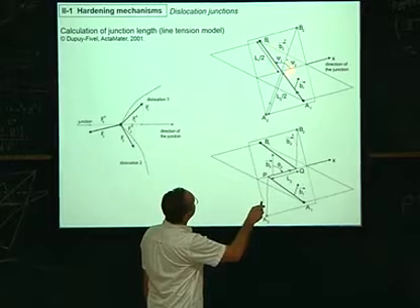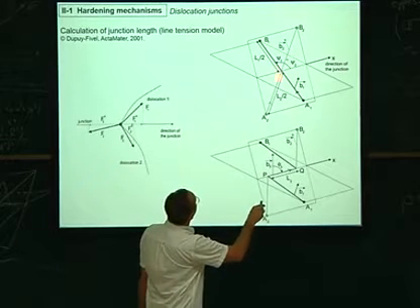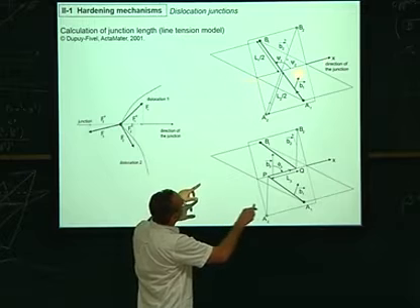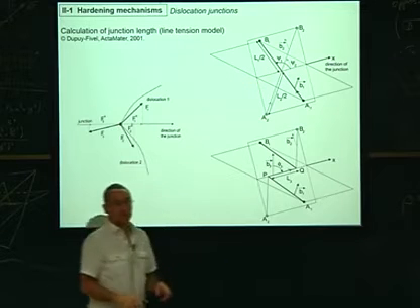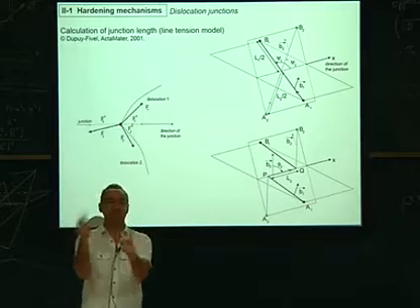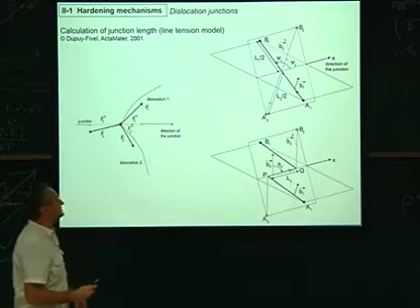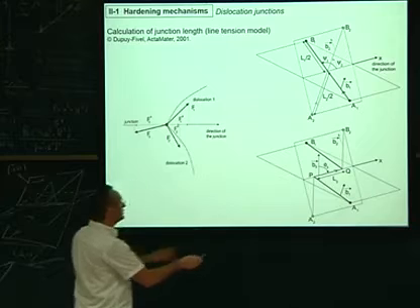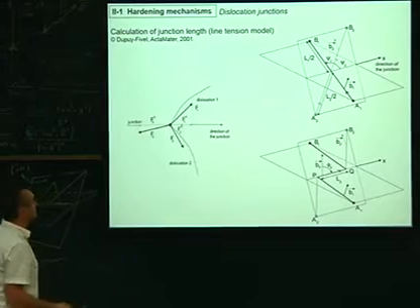So you have an angle psi1, okay, and an angle psi2 in the second plane, which define the angle between the common line and the dislocation line. These are the two parameters we can vary to see all the line orientations, whether they form a junction in space or not, okay? And then later on we can compute some angle, but this is just for strength. I will show you later.